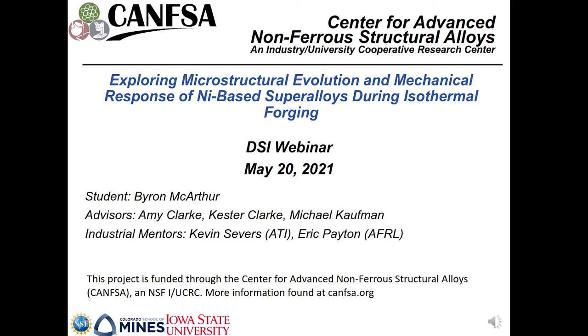In that case, that's where you'd have the higher density, higher driving force, and site availability for recrystallization, as opposed to HRX. The primary gamma primes are predominantly existing at the gamma grain boundaries, so you're not having dislocation looping in that sense. In HRX, you're not so much having the formation of a boundary off of an incoherent interface. You're having this co-oriented, or coherent perhaps to start, but really I'm going to use the term co-oriented because I'm not quite 100% sure on the coherency yet. You have to go into quite a bit more detail on the experimental characterization of that, but co-oriented on that gamma prime as you're dissolving it, or if you're having some dislocation interactions internally that cause that HRX mechanism. So it is definitely a distinct mechanism from PSN.